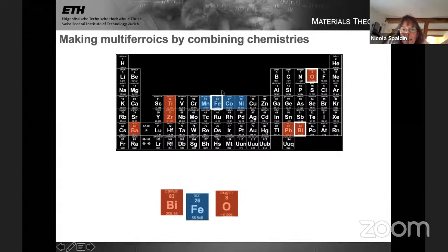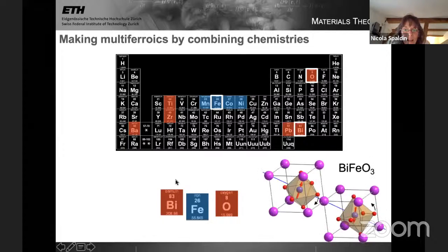So the iron is giving us the d electrons. It's iron 3+, it's D5, so it's very, very magnetic. We have the oxygen, because we're looking at transition metal oxides. And then the bismuth, in this case, is providing the ferroelectricity. This is the structure. It's perovskite structure, so the iron is octahedrally coordinated by the oxygens. The bismuths are at the corners of the unit cells.